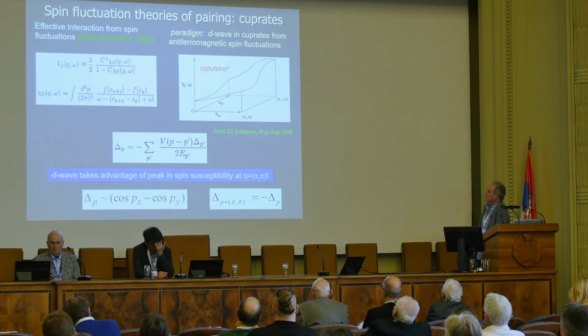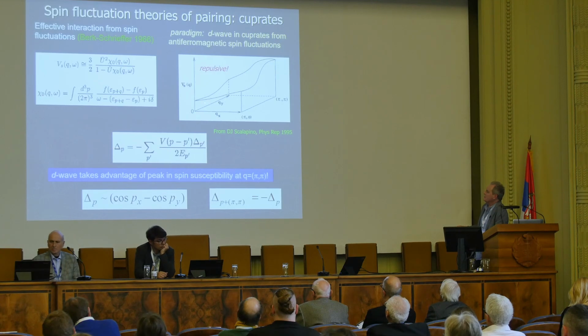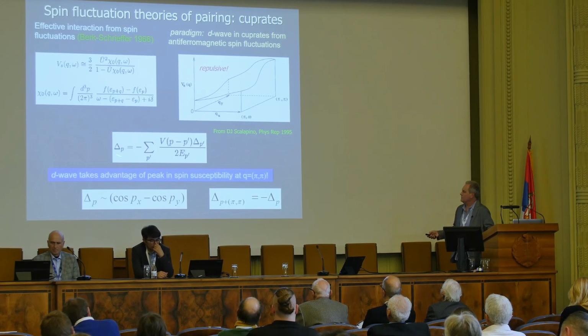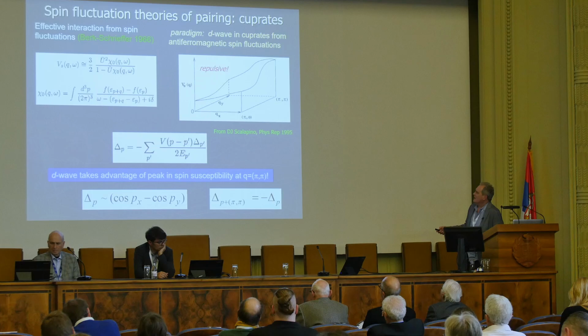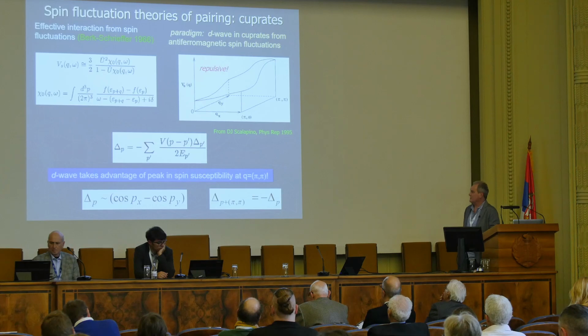So here's what you get if you calculate on a square lattice exactly the same thing. You get an effective interaction between electrons, which has a maximum at pi pi. And notice that it's repulsive everywhere in momentum space. Okay? Now here's the BCS gap equation. I haven't showed this to you before, but take my word for it. That's what this is. I'm going to plug in V of P minus P prime, and I'm going to assume that E is the quasi-particle energy, the energy to create a broken pair state, that's positive. So supposing I try a solution where the left-hand side is positive and the right-hand side is positive, it doesn't work because I have this pesky minus sign out front.